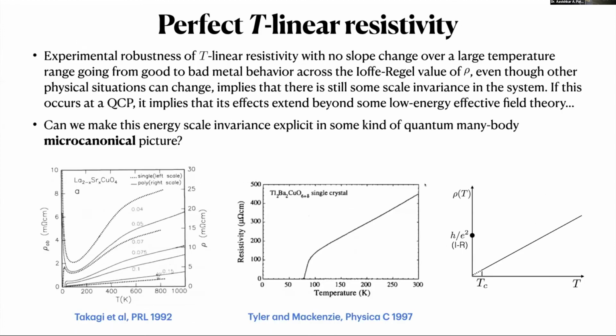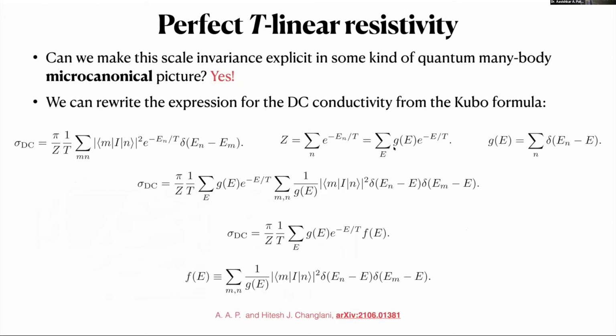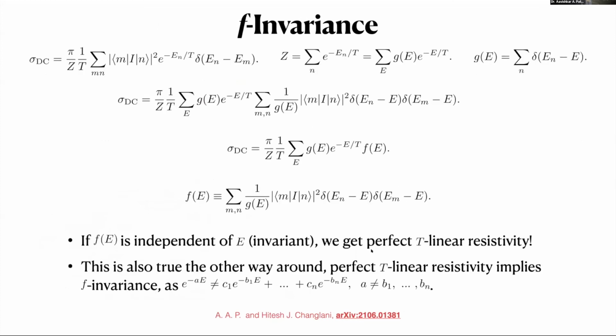right. So quickly, I'll also try to describe, there are many strange metals which have only a single slope of resistivity over very large temperature range. That hints at some kind of scale invariance. So we can derive that. We can actually show that there is a scale invariance just by looking at the Kubo formula. Rewriting of the Kubo formula, where I is the current operator and Z is the partition function, leads to this quantity f of E. And if this f of E quantity, which is defined in the microcanonical ensemble, is completely independent of the energy scale, one gets exact T-linear resistivity.